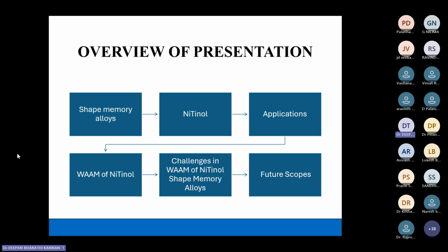It was discovered in the early 1960s by two scientists, William Buehler and Frederick Wang. It has three unique properties, namely shape memory effect, superelasticity, and very good biocompatibility. If it is processed properly, it is possible to recover around 8% strain from nickel titanium shape memory alloys. In the current commercial market, around 90% of the shape memory alloys are nickel titanium alloys, along with nickel titanium copper and nickel titanium niobium alloys.